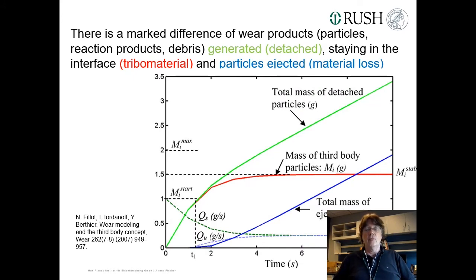Yves Berthier from Lyon, who worked with Maurice Godet when he generated his third body model, was able to quantify that. He says there is a total mass of particles that detach from the surface, and that does not mean that they leave the system, because only the particles that leave the system can be pronounced as wear loss. Everything else which stays in the system is not wear loss, it's still there. So he quantified that if a certain amount of mass is detached from the surface, a certain amount of mass is ejected from the system, which is the wear loss, but in between, these are the third bodies that stay in contact.